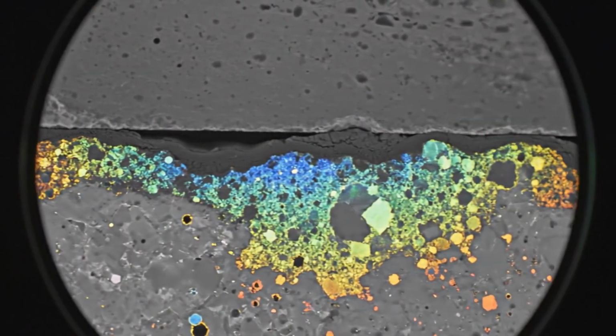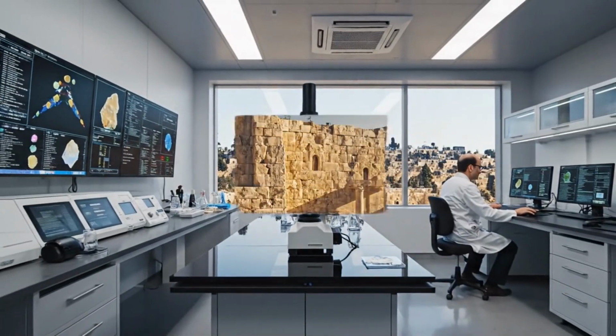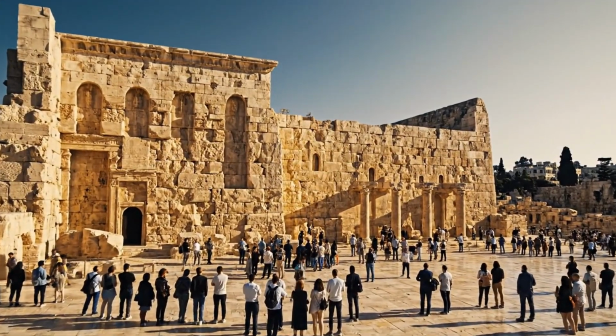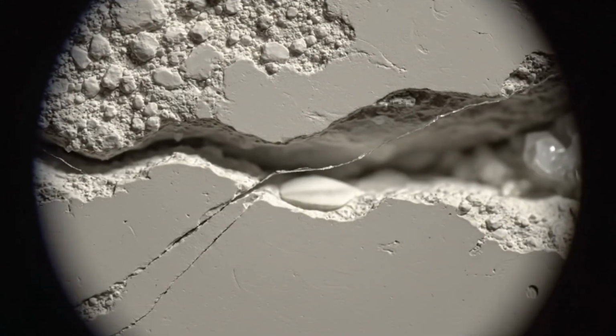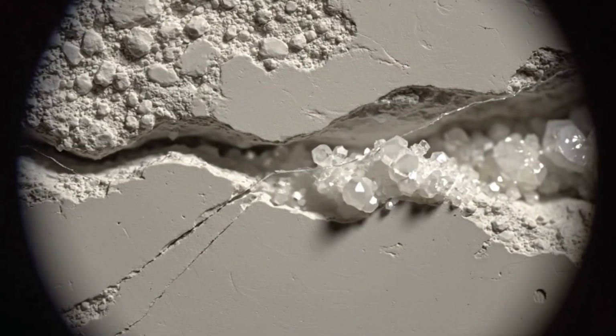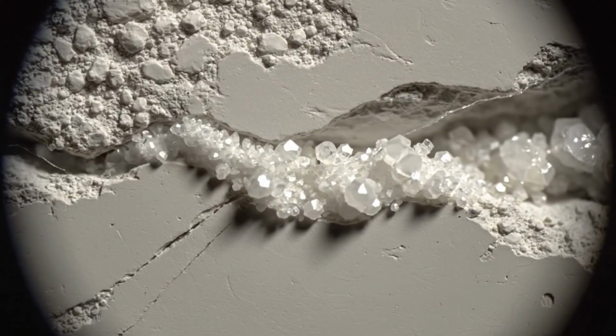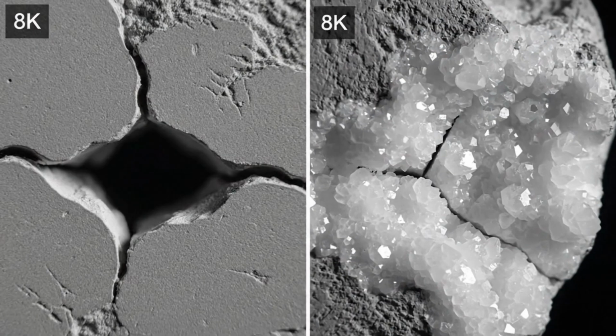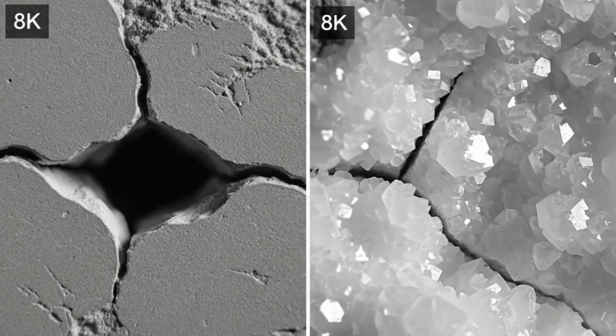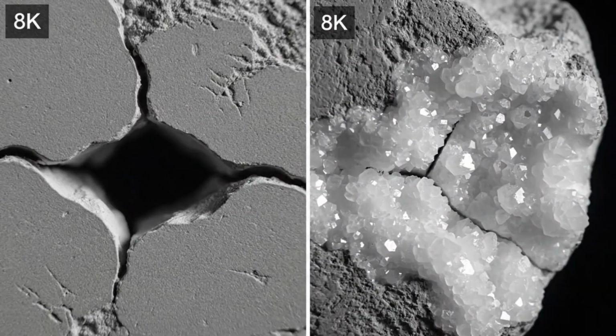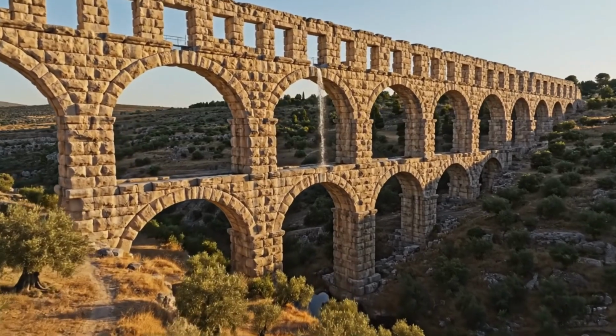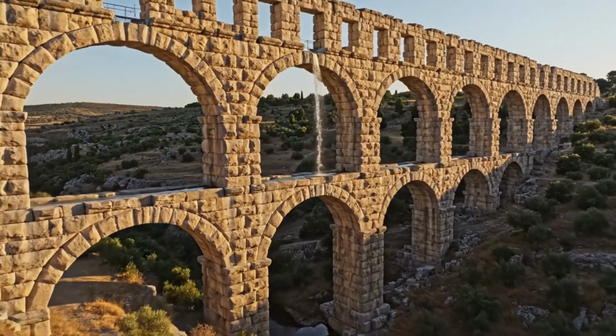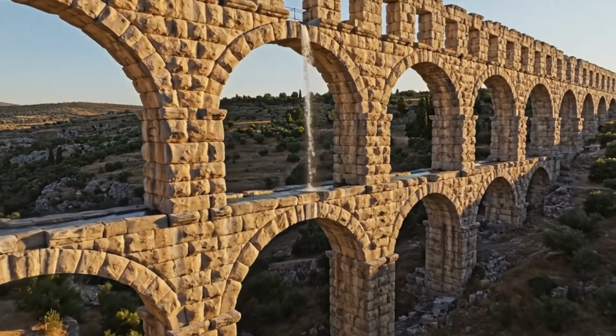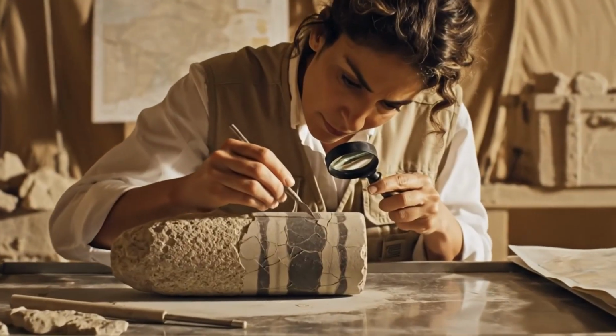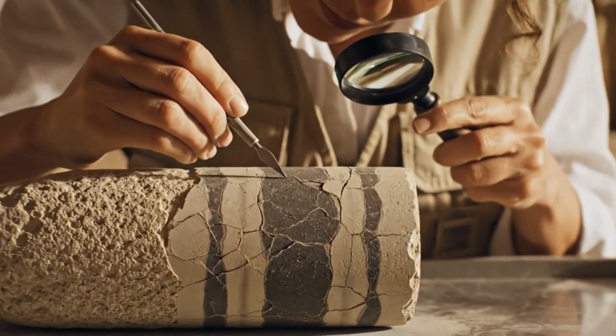The entire wall, stone and mortar together, undergoes the same slow transformation, becoming denser and harder with each century, a self-improving system. The chemistry can be described as a single reversible reaction. Calcium hydroxide plus carbon dioxide yields calcium carbonate plus water. Carbonation hardens the mortar. Calcination, the reverse, is how limestone is burned to produce quicklime. The entire cycle is a closed loop. Limestone is quarried, burned to lime, slaked with water, applied as mortar, and absorbs atmospheric carbon dioxide to become limestone again. Over centuries, the mortar joint becomes mineralogically indistinguishable from the stone. Under a polarizing microscope, a well-carbonated lime joint shows the same calcite crystal structure, grain boundaries, and optical properties as the adjacent block. The joint has ceased to be a joint.